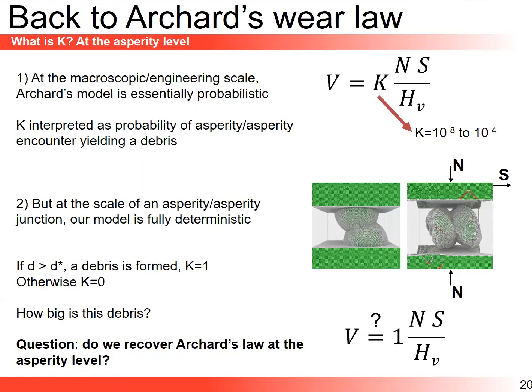Okay, so now let me go back to Archard's law. As I told you, Archard's law requires this unfortunate K factor, which is called the wear coefficient. It varies widely in values. It's viewed as a probability. For us, it's not a probability anymore. If we are at the scale of an asperity, here we're looking at an asperity, if I pick the geometry of the asperity to be larger than D star, we know we're going to form a debris, and therefore we have 100% probability of forming a debris, and K is equal to 1. If not, K is equal to 0. So K is not a fudge parameter for us anymore, it's 1. And we can ask the question, do we recover Archard's law, that the wear volume is N times S over the hardness? So we can ask this question.